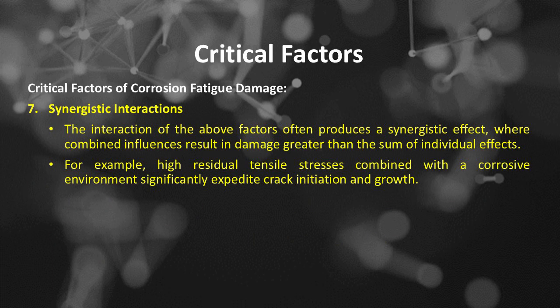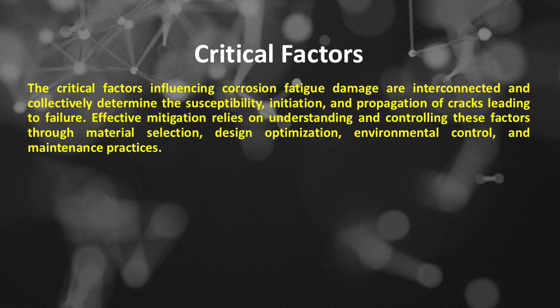Critical factors of corrosion fatigue damage. Number 7 is synergistic interactions. The interaction of the above factors often produces a synergistic effect, where combined influences result in damage greater than the sum of individual effects. For example, high residual tensile stresses combined with a corrosive environment significantly expedite crack initiation and growth. The critical factors influencing corrosion fatigue damage are interconnected and collectively determine the susceptibility, initiation, and propagation of cracks leading to failure. Effective mitigation relies on understanding and controlling these factors through material selection, design optimization, environmental control, and maintenance practices.